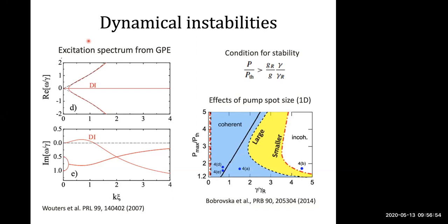But even in the quasi-CW experiments, the recent results from Höfling's group that you showed, the coherence time was longer, as you say, so a smaller line width, but still nowhere close to what you can get for a normal dye photon laser, right? So I believe the line width in that experiment is on the order of about 100 micro eV.